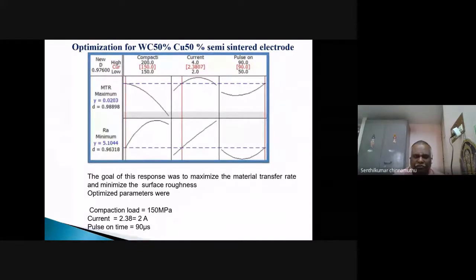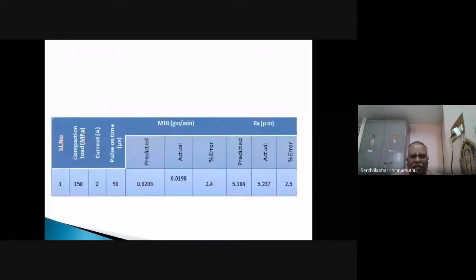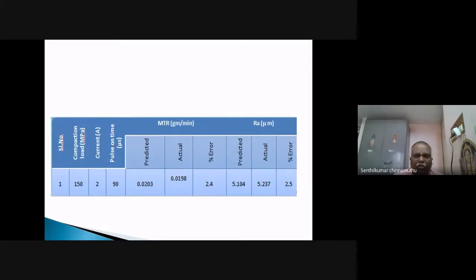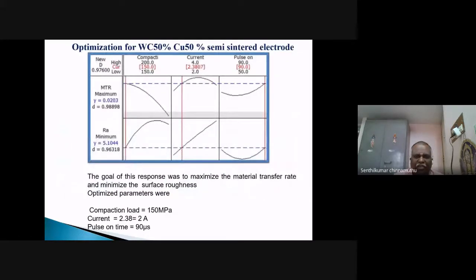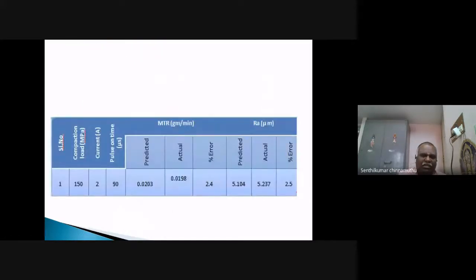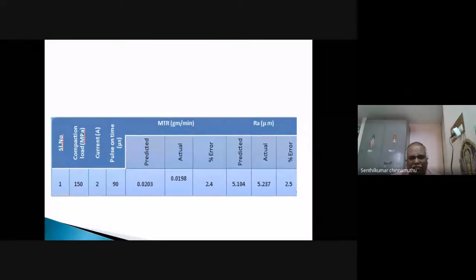The validity experiment has been conducted using the optimized parameters: the compaction load of 150 megapascal, pulse on time of 90, and the current 2.3807, approximately equal to 2 amps, because we could not set 2.38 in the machine. It is not available in the machine, so we have to approximately take 2 amps. And the 0.0203 and 5.104 are predicted from the RSM optimization.